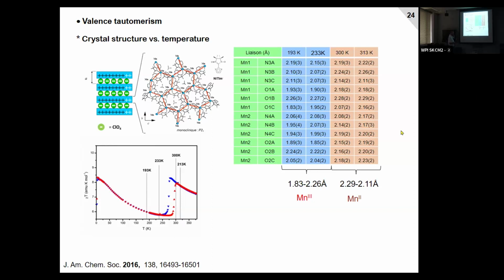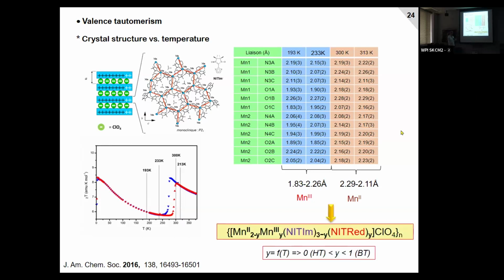Manganese 3 is not isotropic in the bond length. You always have long bond lengths and short bond lengths. So this means that we have a system of manganese 2 that becomes manganese 3. So we have manganese 2 with radicals, and manganese 3. If you have manganese 3, this means the manganese 2 is oxidized. If manganese 2 is oxidized to manganese 3, something should be reduced. This means that the radicals are reduced. So you have a system in which, when you decrease the temperature, you have the electron moving. The electron moves from the manganese 2 to the radical when you cool, and moves again from the radical to the metal ion when you heat the system.